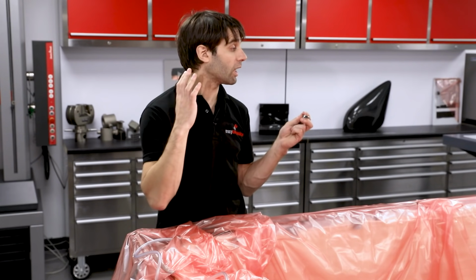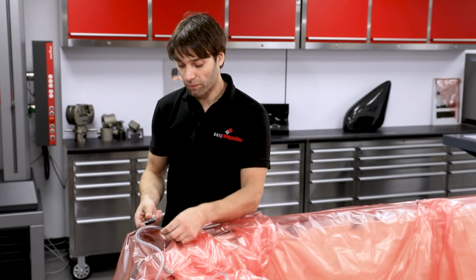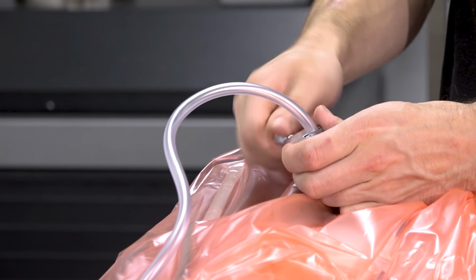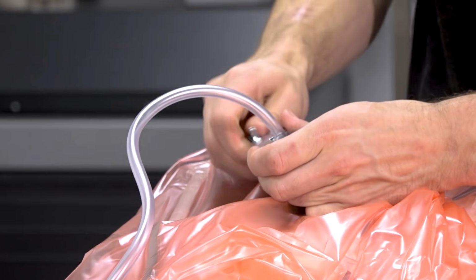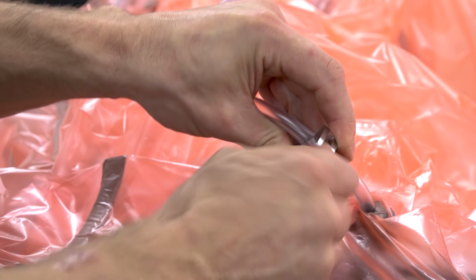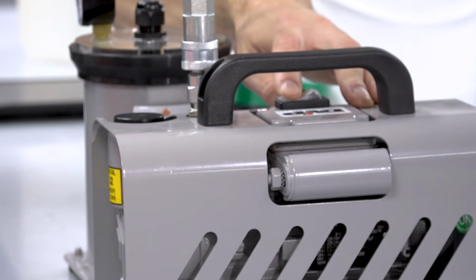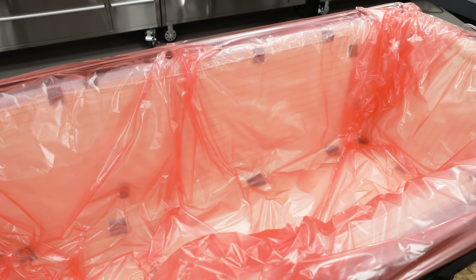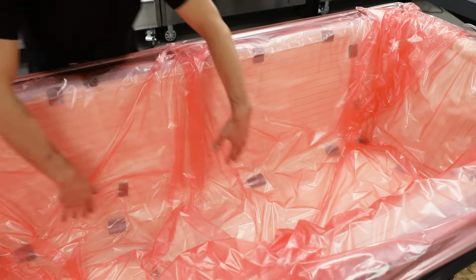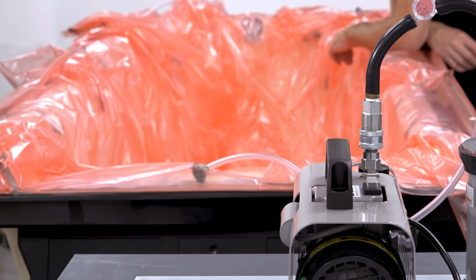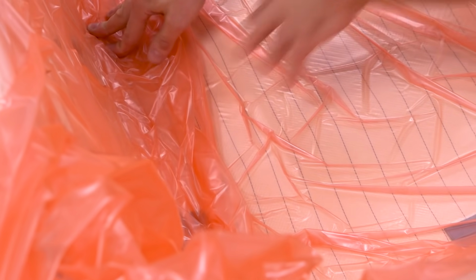We're now at the point that we can pull a vacuum on this. So to do that, we've first got to clamp these lines off, because obviously that is compromising the seal. So we clamp the resin inlets. The vacuum can now be pulled on the bag. This is quite a simple shape, so positioning the bag is quite straightforward. On more complicated shapes, you should gradually increase the vacuum level and position the bag in a few steps. This ensures that the bag and material stack conforms as closely as possible to the mould contours. If you notice an area of bridging, then drop off the vacuum, reposition and try again.